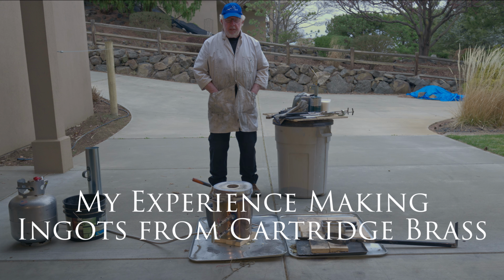Once the lid is on, I want to call your attention to the flame that comes out of the burner. It's barely visible, but it's notable that there's no white smoke. This means we have not reached the critical temperature where you're burning off zinc from the brass. It's important to note that this first heating of the furnace and the crucible and a load of brass is relatively slow. Don't turn the burner up to 10 or 15 psi.